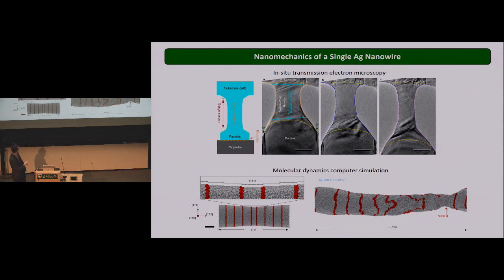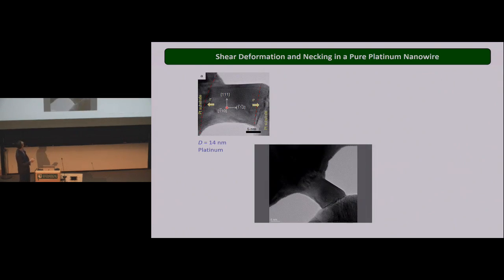Now, you notice I highlighted some atoms in red color. These are just used as markers to see what's going on at the surface of the crystals. If any diffusion happens, you'll see those atoms start to dance on the surface of the nanowire. In this example, it was not the case. Those bands remain just deformed by crystal slip. Right? So let me show you some experimental results. First, in the case of platinum, we wanted to compare two metals.